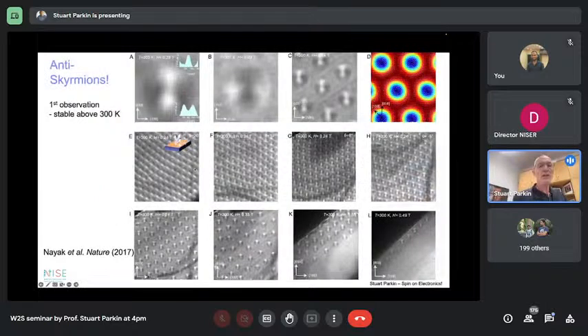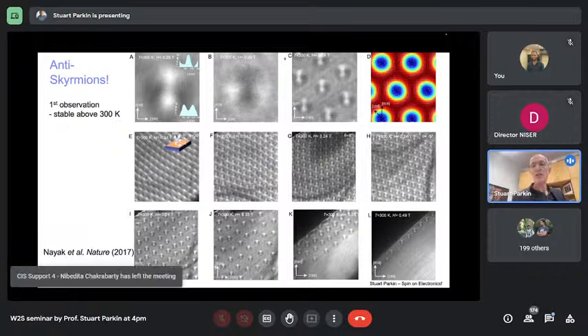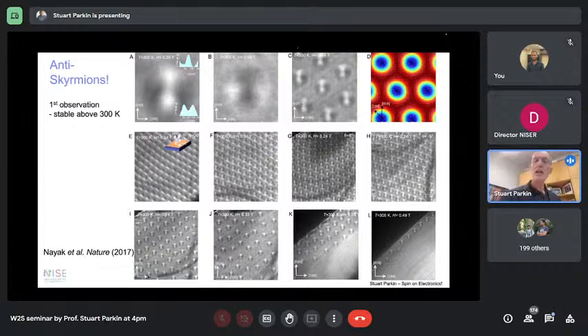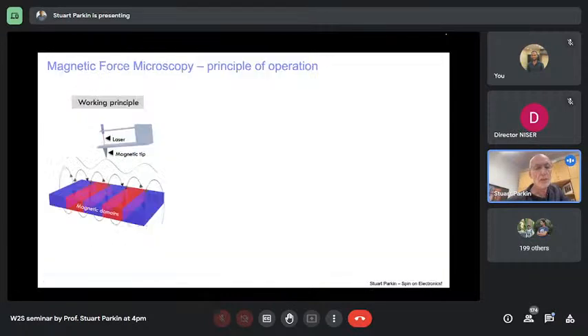At the top left, you can see the first anti-skyrmion directly imaged by Lorentz microscopy, and this we published in Nature five years ago. This is again work by Jai Nayak. And you can see on the top, in C, an array of these anti-skyrmions, a hexagonal array. And in the microscope, we can change the magnetic field and explore the phase stability, and we found that they were stable over a wide range of temperature.